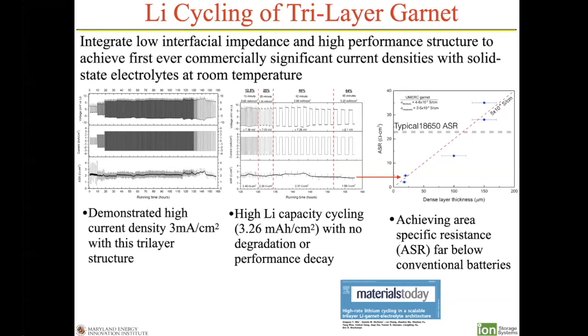With the tape casting, it's quite uniform thickness, so you'll see the error bars are quite small, whereas the other ones are polished discs, and they tend to have greater thickness non-uniformity, and that's why the error bars in thickness are greater. The dashed line in gray is your typical ASR for an 18650 battery. So we are now achieving ohmic ASRs for both the electrolyte and anode interface that are less than that of your typical 18650 battery, enabling the potential for high power density with these solid state cells.